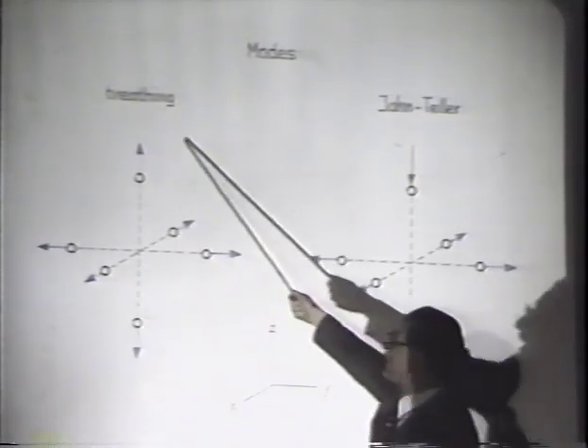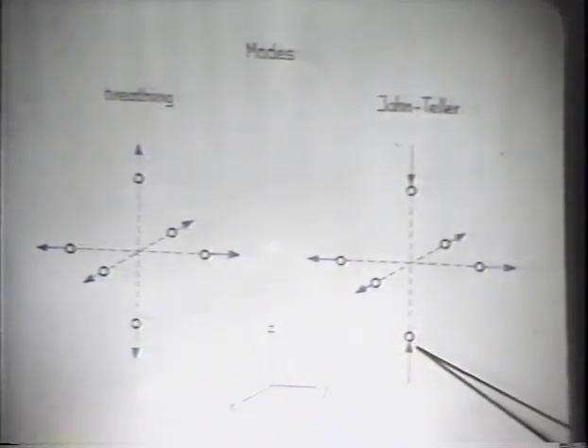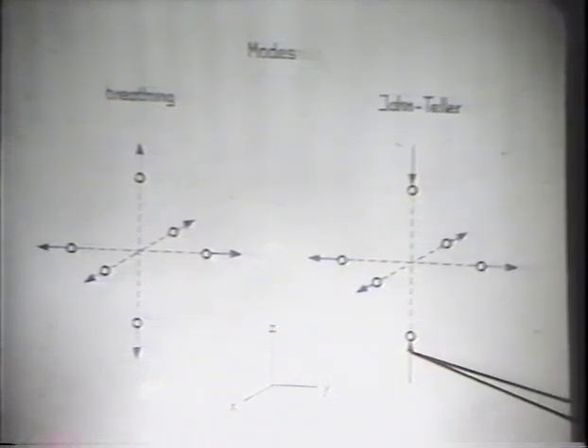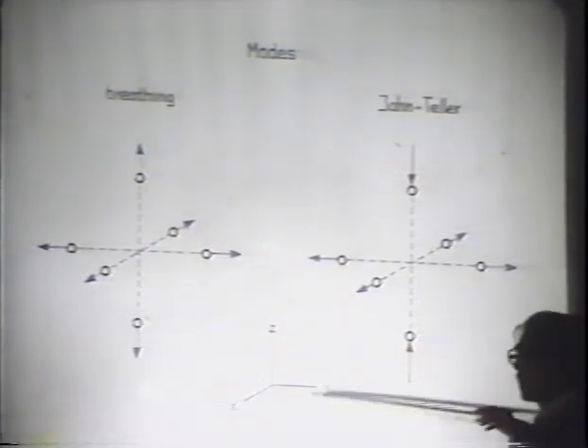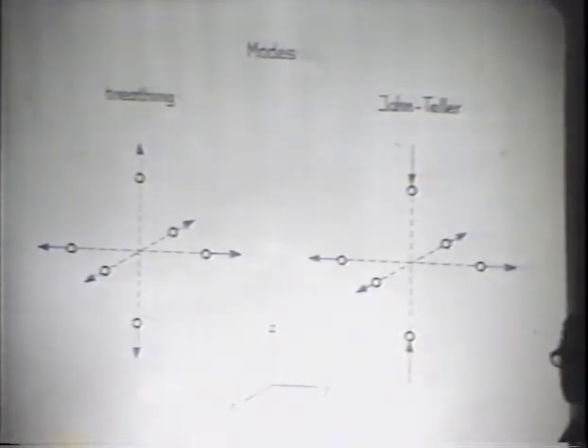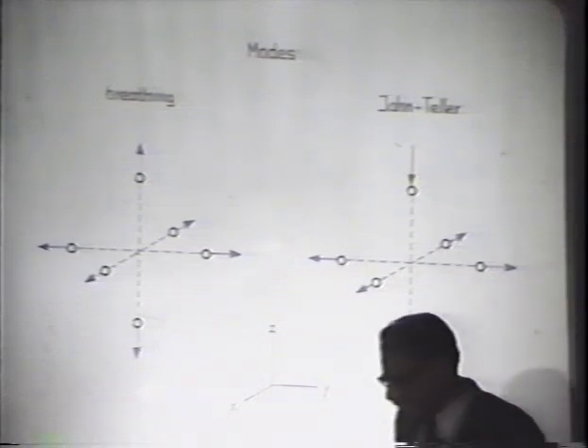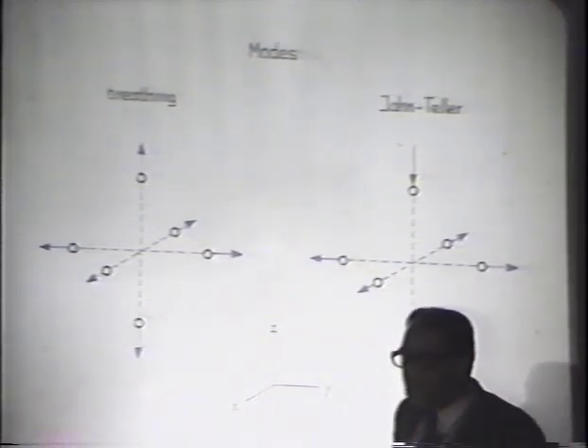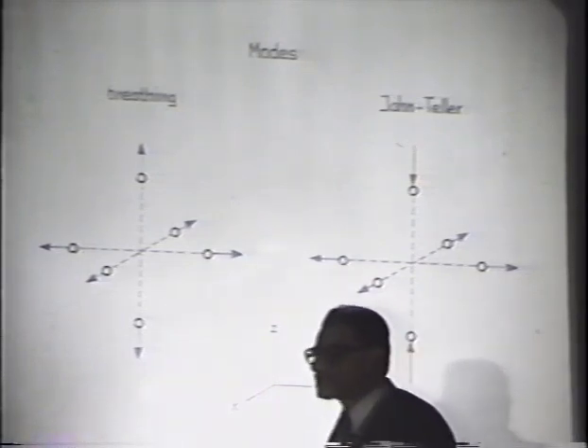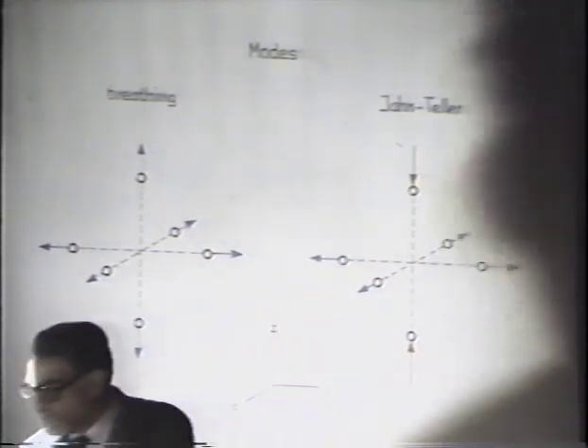You cannot distinguish in the XY plane the motion of the oxygens between the Jahn-Teller and the breathing mode. It's only the out-of-plane motion of the oxygens which is different. Namely here, the red arrows show 180 degrees out of phase, and it's not so much a matter of the amplitude, but of the phase. And to my understanding, there have not been experiments till now to distinguish between these two modes. This mode here preserves the volume of your octahedron, and this may be important because the copper ions in general, as far as I know, do not disproportionate.